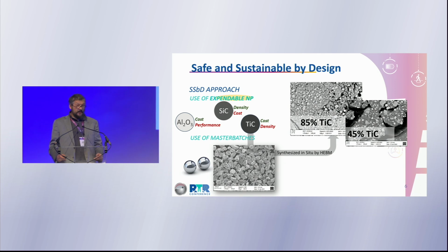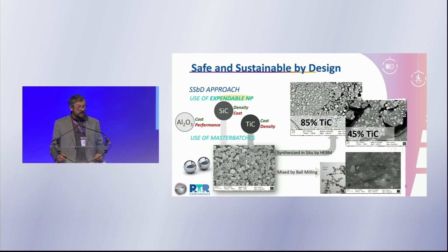So we obtained highly concentrated master batches of aluminum with nanoparticles that can be safely inoculated in a different process of casting and then forging and extrusion of aluminums. Similarly, the idea is also to take nanoparticles on the market, silicon carbide in this case, and mix it with aluminum in a solid state process, in order to create these master batches that can, again, be inoculated in casting and then forged and extruded.